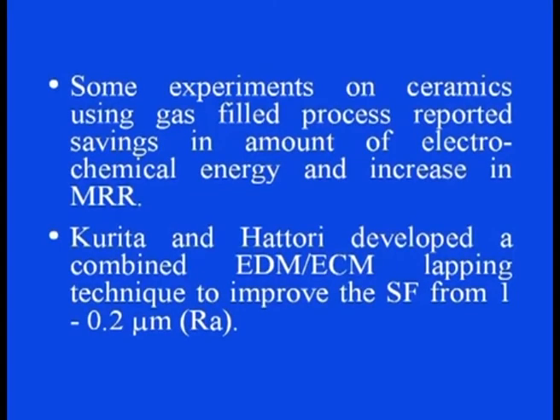Some experiments on ceramics using a gas filled process reported saving in the amount of electrochemical energy and increase in material removal rate. Kurita and Hattori have developed a combined EDM ECM lapping technique to improve the surface finish, in which they have achieved a surface finish of 0.2 micrometer average roughness, which was improved from 1 micrometer to 0.2 micrometer.